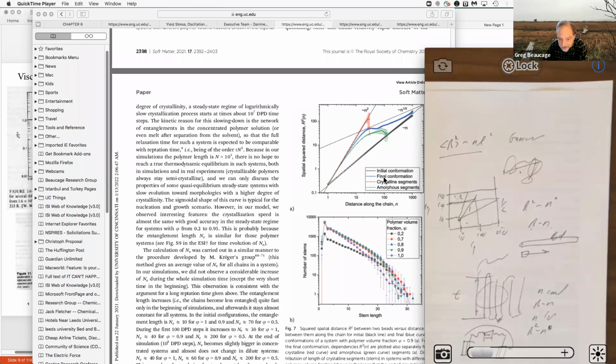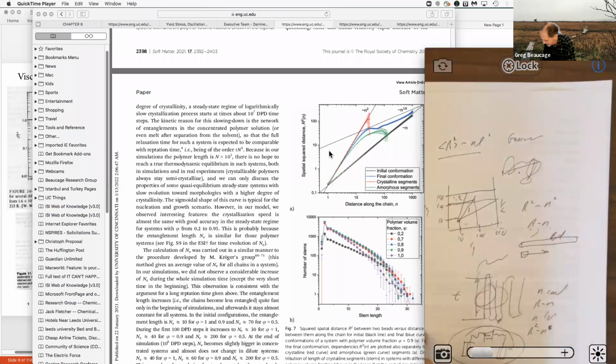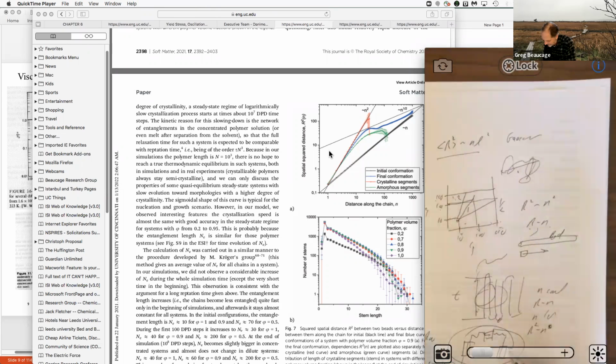You can see, so then he has the final conformation of the chains. So they have this tail over, and then they go to that end here. So this business in here probably has to do with just the transition from the rod within the structure at small scales, and then the connection of these things at large scale forms a random walk again. So that's kind of experimentally verified that you get this random walk on the large scale within a crystalline polymer, and then on a small scale you get this kind of ballistic behavior.